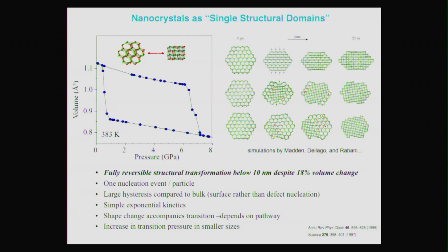One way, in fact, and I wanted to show this story simply because it does relate to what Keith said, what I was doing myself here with my students at SLAC in the early 1990s at SSRL was studying phase transitions in nanoparticles. So we took small crystals and we placed them at very high pressure, and we tried to see, would a phase transition occur when you squeeze on it, and we did those kinds of experiments right nearby here. And what we found at that time was that if we took a very tiny crystal, we could often super pressurize it beyond any structural pressure by an enormous amount than anyone had expected, simply because the crystal contained no defects at which nucleation sites could occur to induce the transition.